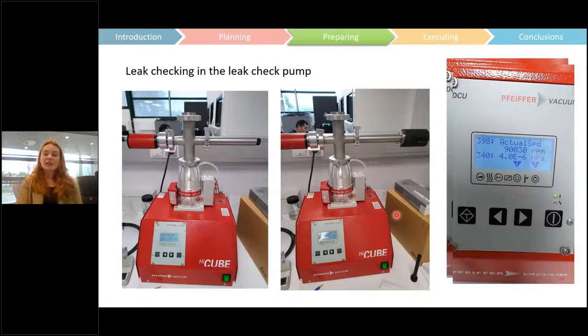So for leak checking, we use a HiCube. If you have a HiCube, that really helps. We usually pump our HiCube without a holder in, so just with a stub in first, just to make sure that it does go down to the value that we want it to go down to, which is at least 4 e⁻⁶ hectopascals. That's the main goal for us. And then we would switch to the holder. So we put the holder in with the back closed, and we pump that down for 15 minutes, until it reaches that value. And then we open the back of the holder.